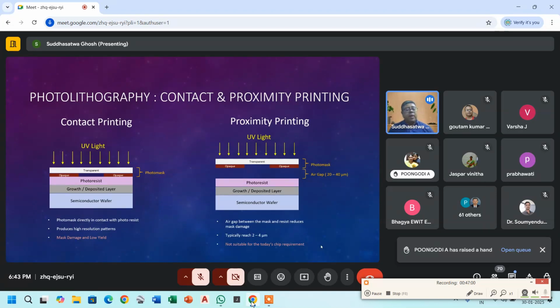In the past, they were the original type of photolithography equipment made based on these concepts. The defining resolution was basically how small you can make the features on the mask. This contact printing was quite effective, making features at the sub-micron level on a device. But one of the main disadvantages is that, since the mask and the photoresist are in contact, after multiple reuses the yield goes down, and it also puts defects on the mask, which has to be cleaned. It's a tedious process, not really useful to be followed.